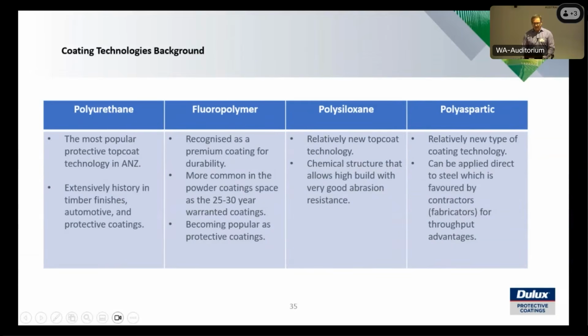Polysiloxane provides very good abrasion resistance and very good cleaning ability with those, and you can apply high builds with that particular type of technology coatings, and that can sometimes limit what might be a 3-coat system to a 2-coat system. So it's all about, again, getting back to practices about achieving results depending on the type of project. Polyaspartic, relatively new, but it is out there globally and in Australia and New Zealand. You probably also come across it nowadays in a lot of flooring coatings as well. You'll probably see it. So they use that for quick processing and quick return to service type environments.